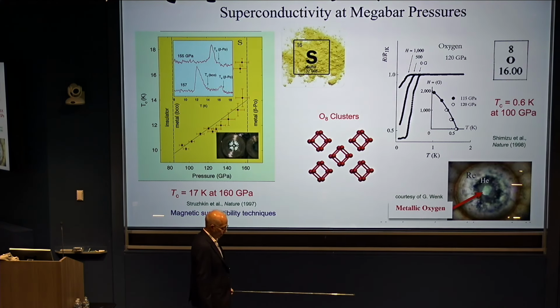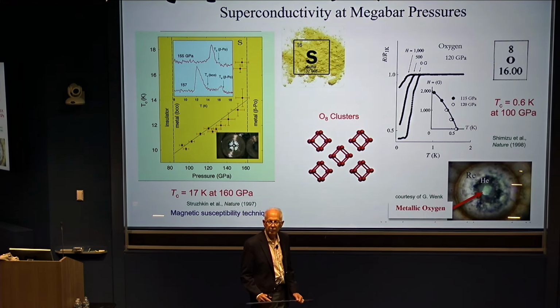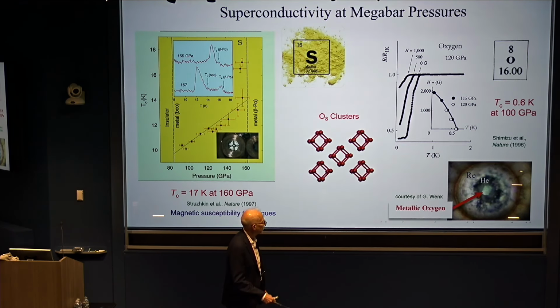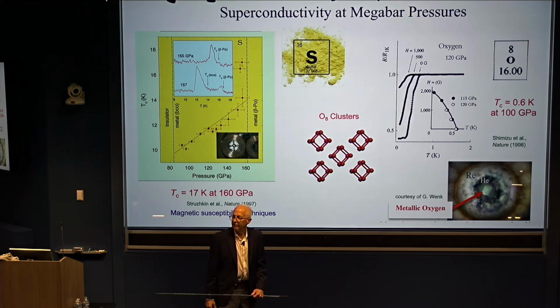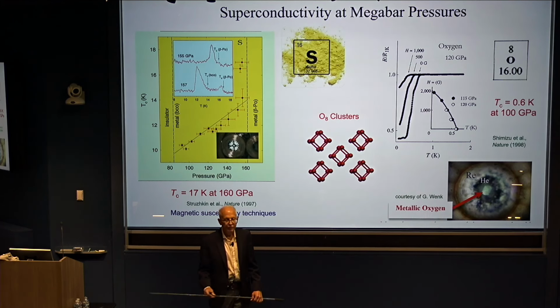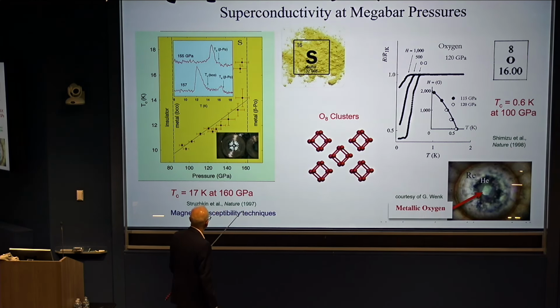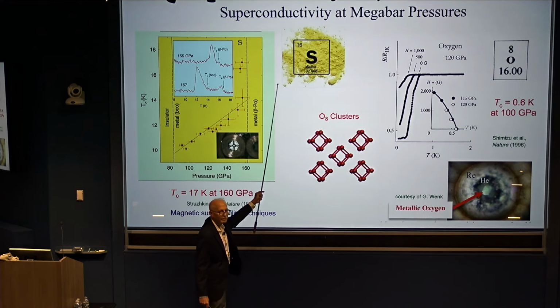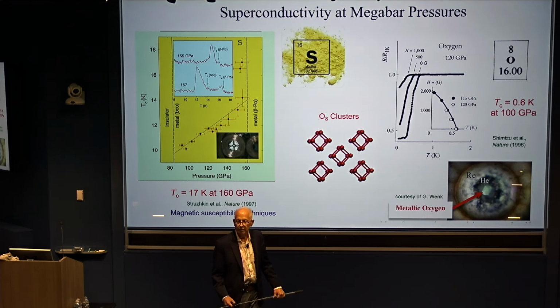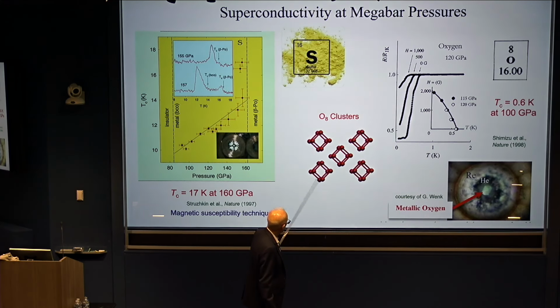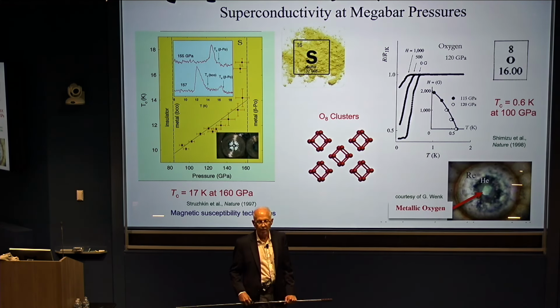Well, this drove a lot of the field, and when I started working in this high pressure field back in the 80s, this caught my interest. And during the 90s, we developed a number of techniques for studying various materials and elements, in particular under pressure, as a starting point. We developed some techniques using this magnetic coil technique to study sulfur. We found that sulfur, common ordinary sulfur here, this yellow powder, can be turned into a superconductor. It's a pretty nice superconductor. It's got a TC of 17 Kelvin, not much compared to the hot superconductors I was describing, but at the time, this was the highest temperature superconductor of an element.